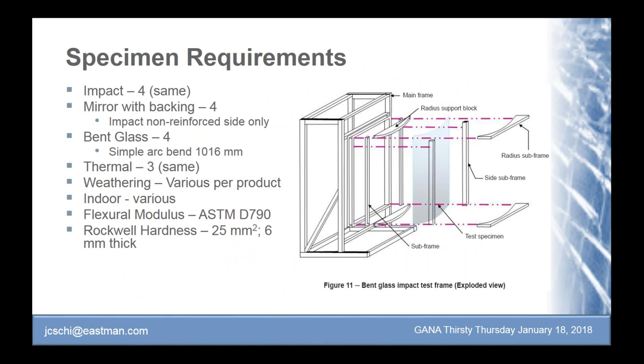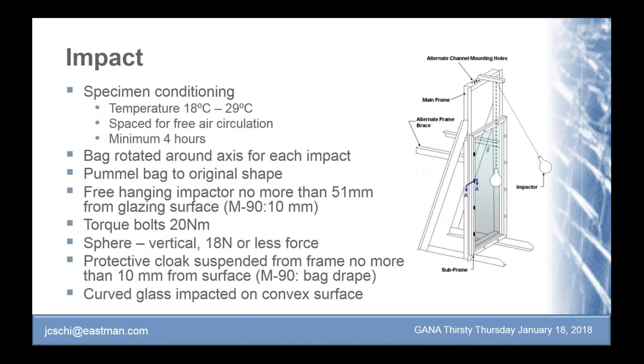The specimen requirements are the same as they were. You test four units. Mirror with backing, you only have to impact the non-reinforced side. Bent glass, there's a simple arc that is allowed so that you don't have to test every single arc. There's three samples tested for thermal, which is the same. Nothing has changed. That would be the bake and boil. And the weathering does change based on the products because of the end test after the weathering has occurred. So you have to reference the standard to understand those. And then the plastics testing. So there really isn't a lot of change in the specimen requirements to the Canadian standard, with the exception of the weathering samples.